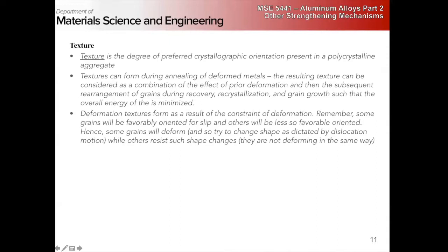Deformation textures form as a result of grain rotation during our deformation, and some real common ones are rolling textures or extrusion textures. Each deformation mode gives a stable different orientation, and because our polycrystal, or single crystals, are anisotropic plastically,